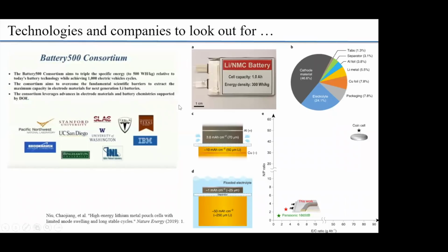And then there's the Battery 500 Consortium, which comprises Stanford researchers, like Professor Yi Cui and many others. There is Binghamton, which has Professor Whittingham, the Nobel laureate, UT Austin, Professor Goodenough, Tesla, IBM, Idaho National Lab. So really a great team of scientists. And they put out this paper in 2019. They were able to make use of lithium metal and NMC, and they were able to push the energy density to 300 watt hours per kilogram. They did it by keeping the electrolyte.